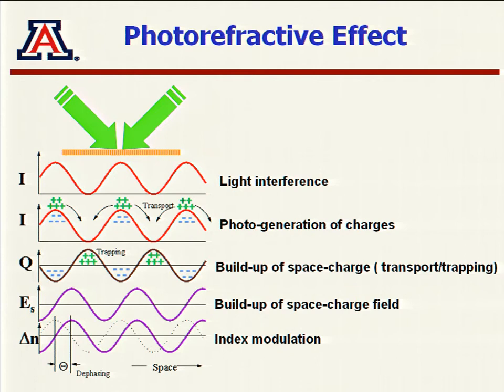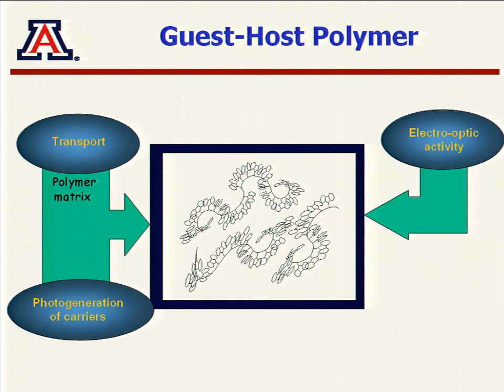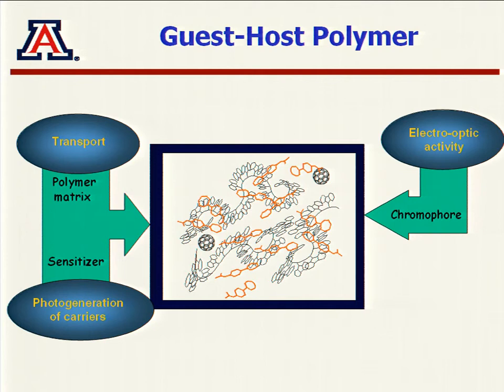For this process to work, the material needs various properties: charge carrier generation (photosensitivity), photoconductivity, and electro-optic properties. All of that can be obtained in polymers through what's called the guest-host approach — you start with a host material, a photoconducting polymer matrix, and add different guests. For example, we start with PATPD as the matrix, then add nanocarbon as a photosensitizer so that charge carriers are generated by shining light on it, and add nonlinear chromophores to make the material electro-optically active.